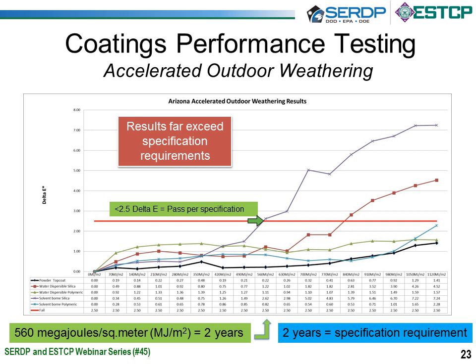The traditional coatings barely passed the specification. Some improvements were made to coatings over the years that got much better when we started getting into polymeric flattening agents and liquid coatings. Then the powder coating was developed. The first qualified product we developed is right here. The black line is our black powder coating.